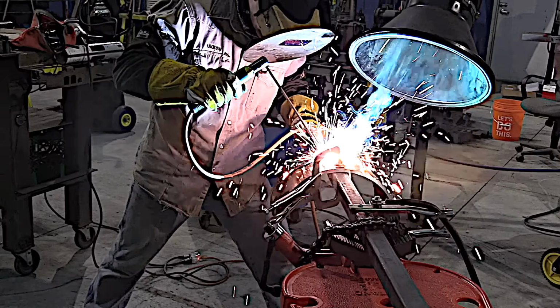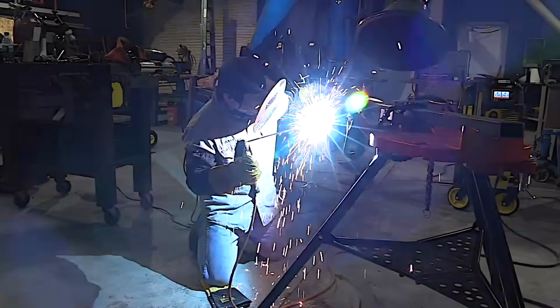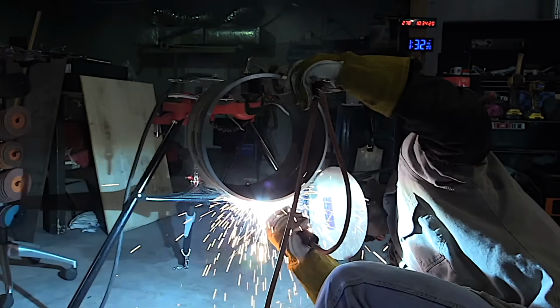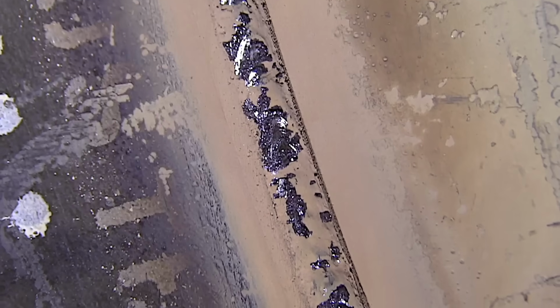Here's a hot pass on that 12-inch pipe. Incidentally, hot pass goals are mainly don't leave any voids or slag behind or cold lap or anything, but also don't blow through, don't remelt, don't reconfigure the good root you just put in. So that requires a little bit of skill in body positioning, how to move out with adequate speed, hold the right angle, the right arc length, so you don't screw up the root pass.